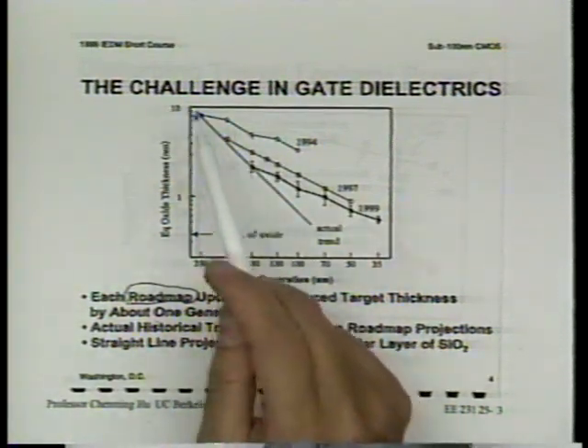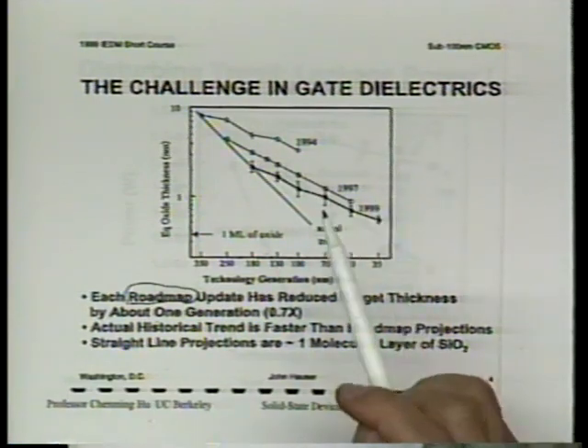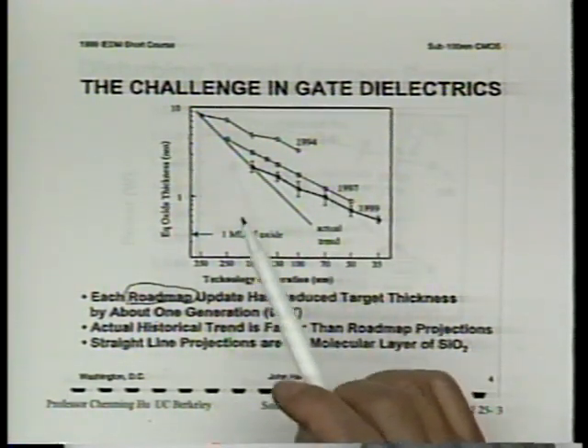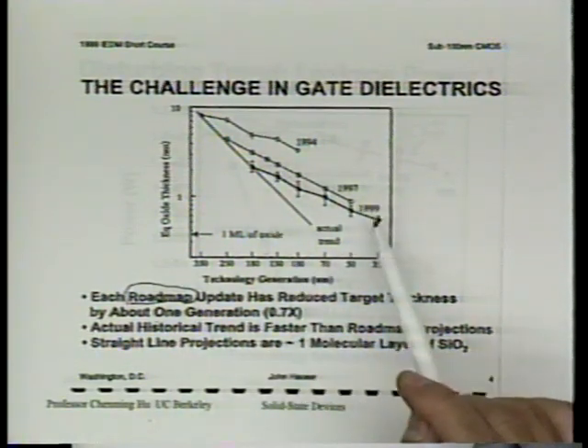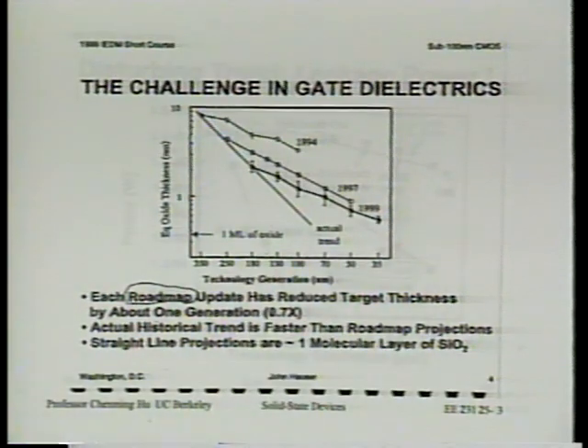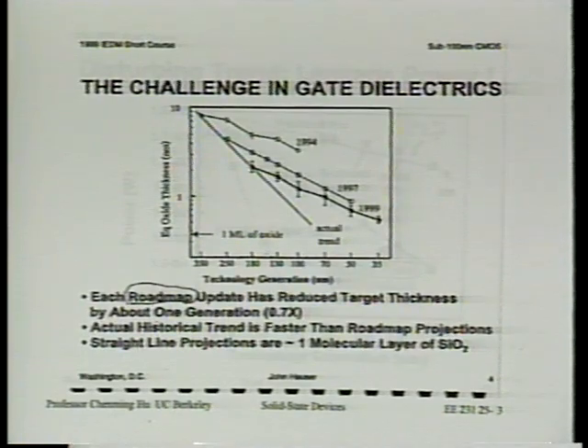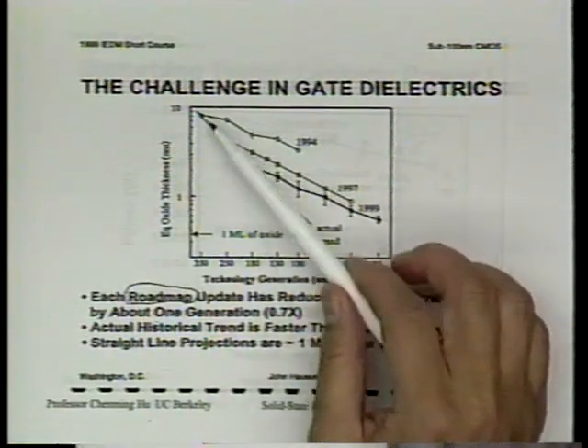Publications show companies using less than 10 Angstroms, meaning gate leakage current density on the order of 1000 A/cm² — comparable to the current density allowed in copper wire. Many people therefore conclude the end of SiO2 gate oxide scaling is in sight, due to tunneling leakage current becoming too large below about 20 Angstroms.